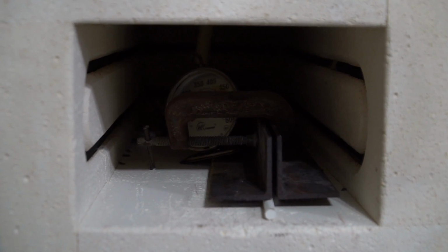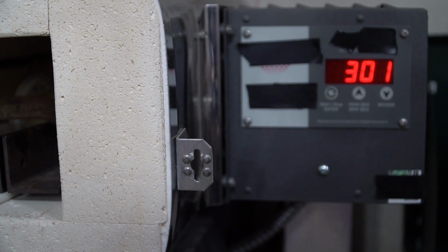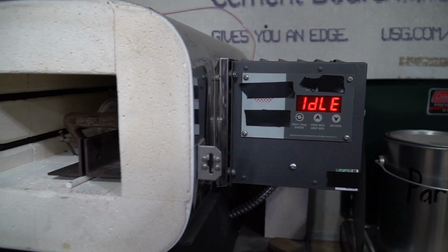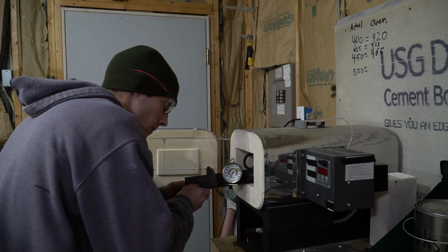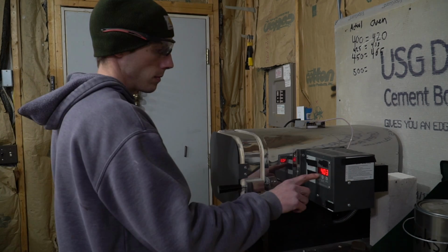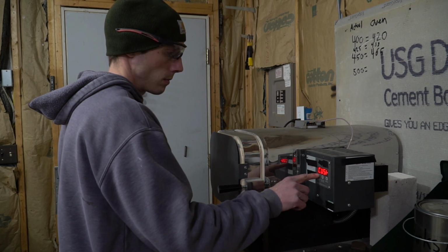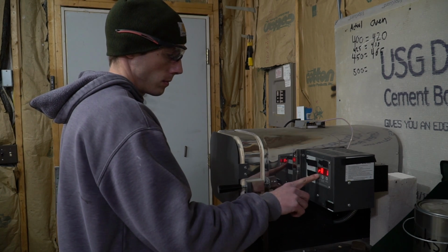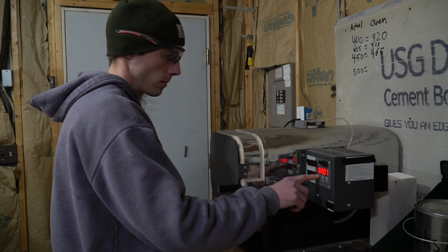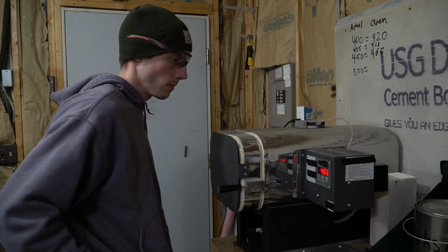We've got our knife in there and the clamp, and our oven's cooled down enough. We will watch this as we heat up, make sure we don't overshoot our temperature, and we'll start our temper cycles. And here's our temper cycles. Cycle 1 was at 415 degrees for 2 hours, and then we remove it and let it cool to the touch. The second cycle was 415 degrees for 2 hours, remove and let it cool to the touch. My oven holds the temperature fairly accurately once I dial in the display for what's actually happening inside the oven. If your oven varies between, say, 400 and 425, don't sweat it too much. It'll be close enough.